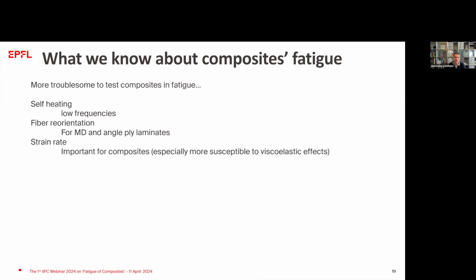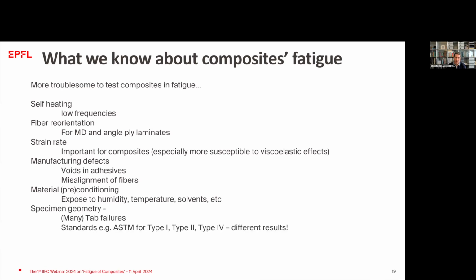We have an important effect of strain rate on material behavior, and it is more significant when we have viscoelastic components, such as thermoplastic composites or epoxy composites with a quite ductile matrix. We have problems with voids in adhesives, misalignment of fibers during manufacturing, or manufacturing defects that can affect the performance of the material a lot. We have material preconditioning problems because the material is very sensitive to temperature, solvents, and humidity. So the material and the testing environment should be controlled to avoid all these effects. We have problems with specimen geometry and a lot of tab failures in composite or adhesive specimens.